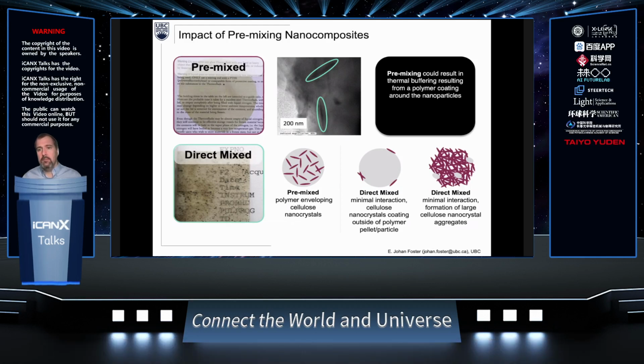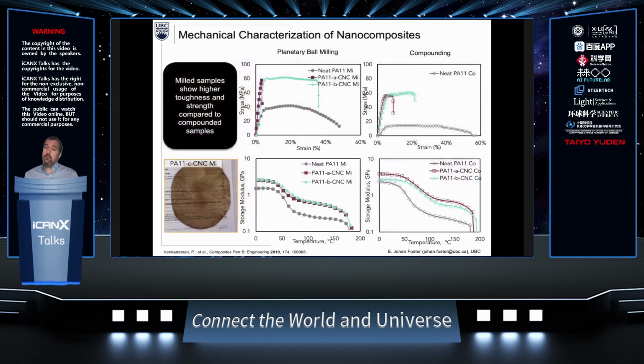Okay. So it's a very interesting trick to be able to take these cellulose nanocrystals and mechanically push them into the polymer at low temperatures, and then use that as a kind of master batching, as a method to be able to get this into larger polymers. Okay. What happens? Well, we get fantastic mechanical reinforcement of the polymer itself. Again, if you do this in the right way, or if you use the right cellulose nanocrystals, you can get the thermal stability. Not all cellulose nanocrystals are the same.